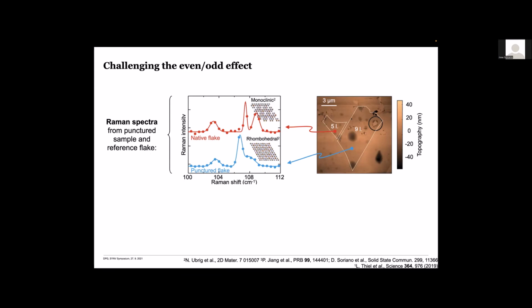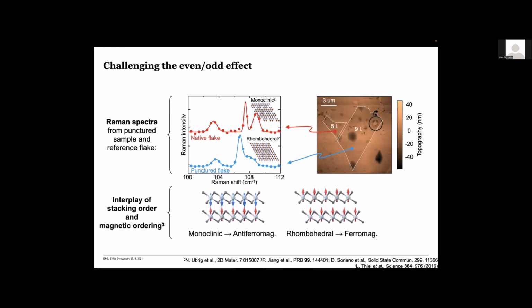And as it turns out, if you look into literature that is existing on this material, these 2 Raman spectra are consistent with 2 different stacking orders, one being monoclinic and the other one rhombohedral. And then again, if we go back to theory and compare to the expected interlayer magnetic coupling for these 2 cases, one sees that the monoclinic stacking is supposed to be antiferromagnetic, whereas the rhombohedral leads to ferromagnetic stacking. So this is for us the explanation for this even odd effect.